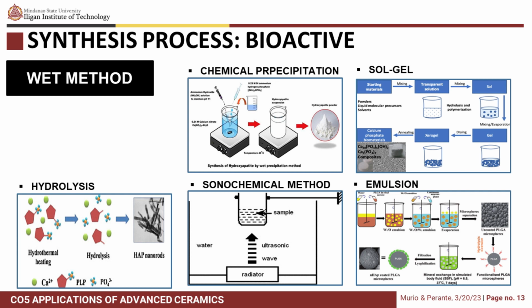During the sol-gel process, a sol, which is a colloidal suspension of solid particles, is transformed into a 3D network of solid phase. In this method, precursors, generally alkoxides, are mixed, then aged, gelated, dried, and calcinated to remove organic residues. Using the hydrolysis method, hydroxyapatite is obtained by transformation of different calcium phosphate phases, mainly in an aqueous solution. Hydrothermal synthesis can be described as a chemical precipitation taking place at higher temperature. In this method, organic modifiers are often used to control morphology and structure of the obtained crystals. Sonochemical methods allow formation of uniform particles, which always yield nano-sized products resulting from chemical reactions occurring in the presence of ultrasound radiation.